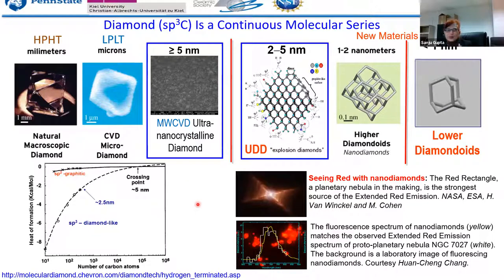I'm using a sort of chemistry language, according to which each carbon is bonded with four other carbons. So diamond, as we all know, diamonds are the best friend of women. With high pressure, high temperature, or natural diamond, we can grow single crystal diamond. Then of course we have micron size diamond, which is grown. The very first patent came from Russia, in fact in 1962. And then there was a little bit of silence till